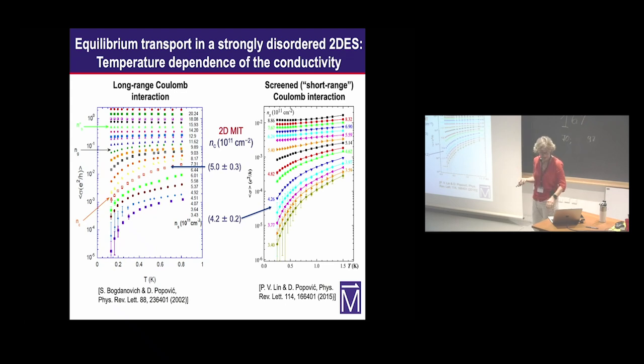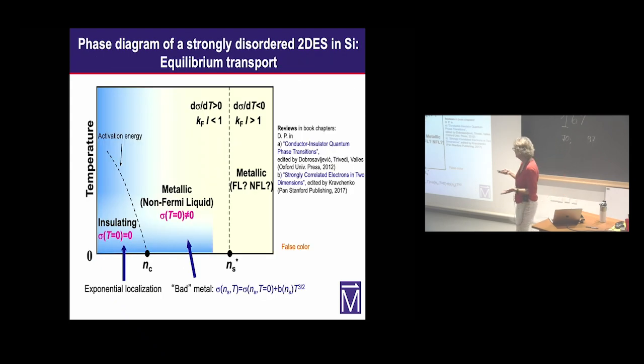Basically, we have looked at the temperature dependence in detail, and this sketch here is a summary of our conclusions. So at the lowest densities, we find exponential temperature dependence of the conductivity, which means that in the zero temperature limit, conductivity is 0. And at higher densities, there is this intermediate regime where we find this behavior. Phenomenologically, we determine that it's proportional to temperature to the power of 3/2. Now, this temperature dependence extrapolates to a finite value at zero temperature, which means that this is a metal, strictly speaking. So again, we are talking about a zero temperature phase transition. The only difference between these ground states is that at zero temperature, in the insulating state, conductivity is zero. On the metallic side, conductivity is not zero.